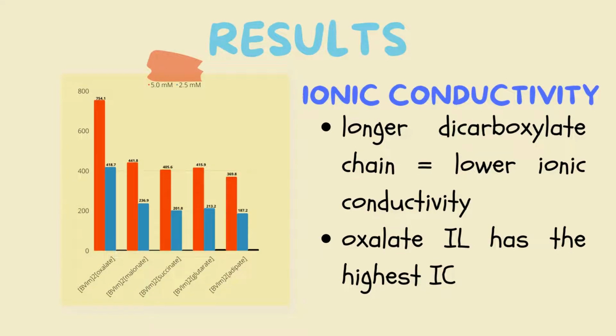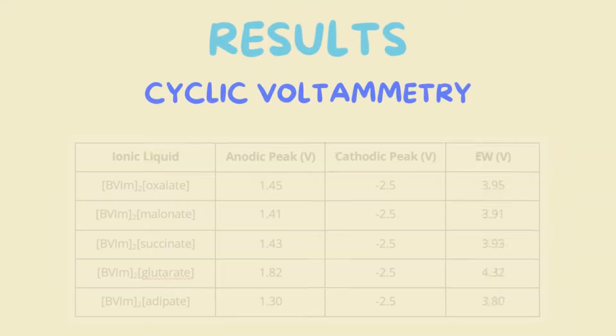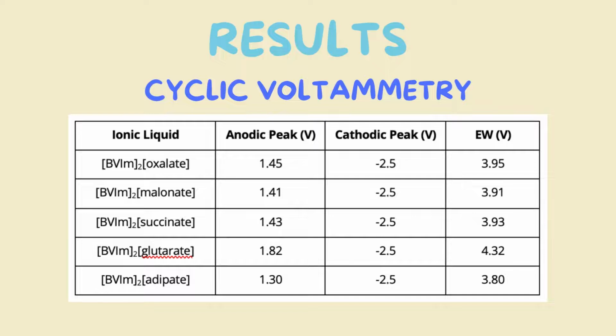For the ionic conductivity tests, it was observed that the longer or larger the dicarboxylate was, the lower the ionic conductivity. This was expected because longer dicarboxylate chains increase van der Waals interactions, leading to higher viscosity and therefore lower ionic motility. The oxalate ionic liquid had the highest conductivity, owing to oxalate's relatively smaller size compared to the other dicarboxylates. As for the results of the cyclic voltammetry, there was no clear trend on the width of the electrochemical stability window with respect to the length of the dicarboxylate anion, but they were all around 4 volts, which is 4 times that of the electrochemical stability of aqueous electrolytes and around 1.5 times that of organic electrolytes.